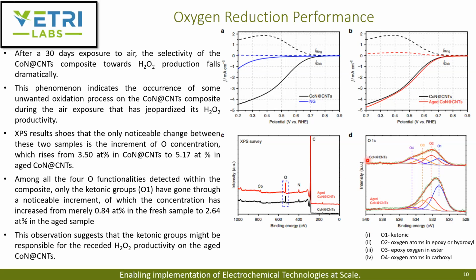And then they did the high resolution scan, so that they could split the different oxygen groups: ketonic oxygen, oxygen atoms in epoxy, oxygen in the ester groups, or oxygen atoms in the carboxyl groups. After dividing into these and measuring the percentage of each oxygen, they could identify that only the ketonic groups have gone through a noticeable increment, increasing from 0.84 atomic percent to 2.64 atomic percent in the aged sample. It's roughly a 3 times increase in their ketonic oxygen.